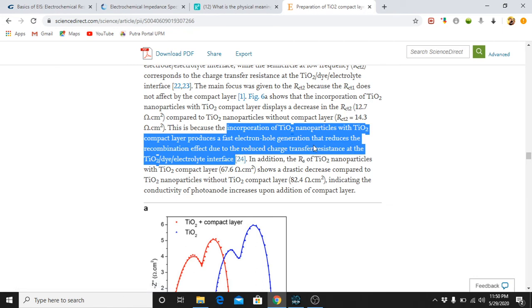You might ask: by adding a new layer between the TCO, the transparent conductive oxide, and the photoanode, like a new door, the electron must pass through another barrier, so why doesn't the resistance increase instead of decrease? However, in this case we are talking about a compact layer, a layer that is very thin, very compact, and very conductive. That's why that layer fastens the electron hole generation and reduces the recombination effect, due to the reduced charge transfer resistance at the TiO2 dye electrolyte interface.